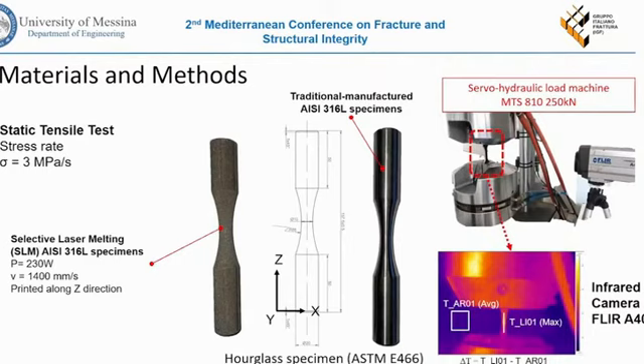So in our work, we tested 2 kinds of materials, the traditional stainless steel and the additive manufactured stainless steel, with the same specimen geometry. We adopted a servo-hydraulic load machine, and we also monitored the temperature with an infrared camera. For the selective laser melting steel, we adopted a laser power of 230 watts and a laser scanning velocity of 1400 millimeters per second. The specimens were built along the Z direction, and the static tensile tests were performed under stress control.